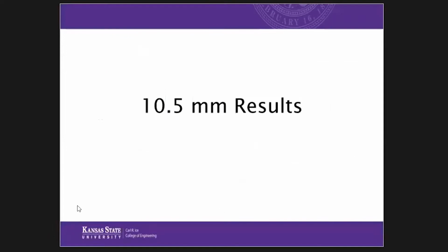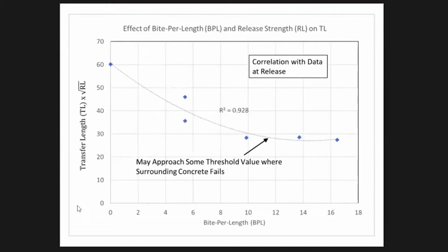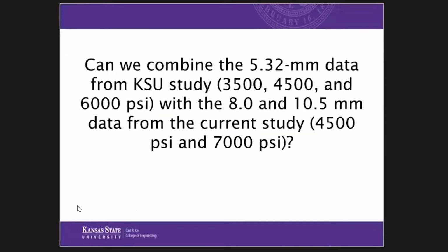For the 10.5mm wires, we see kind of the same thing. Again, I'm plotting transfer length times square root of release strength against bite per length. And again, it comes down to a point and almost forms a horizontal. What's going on there? I think at that point, the wire itself can't grip any more concrete. It's not about adding deeper indents or more indents. There's a flat-out shear capacity of that wire. The shear strength of the concrete, it's just going to pull through regardless. Doesn't matter about the indent. So there's a limiting value of bite per length, and anything above that, I think, is just causing issues.